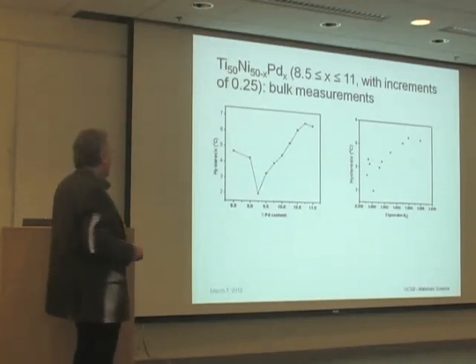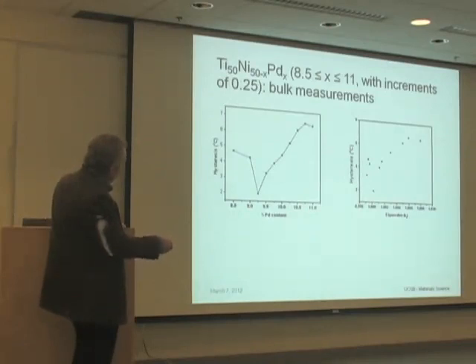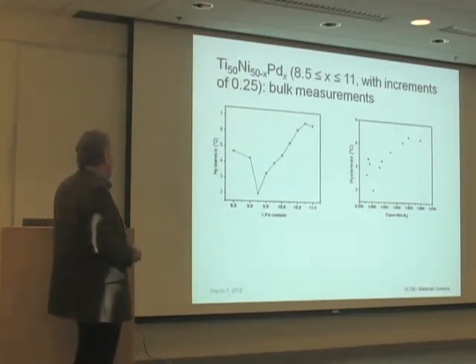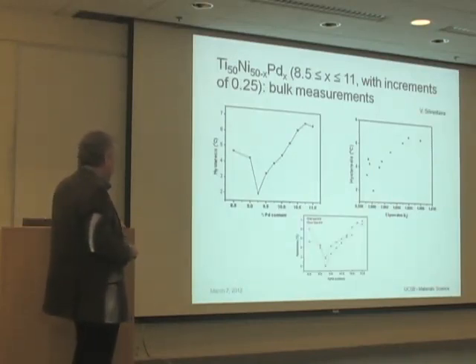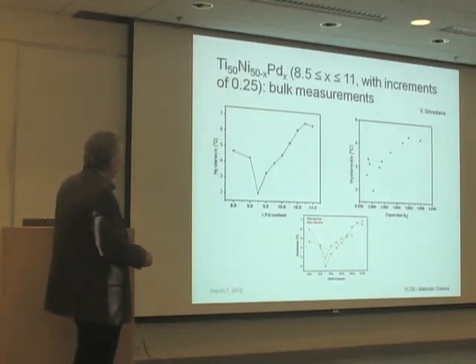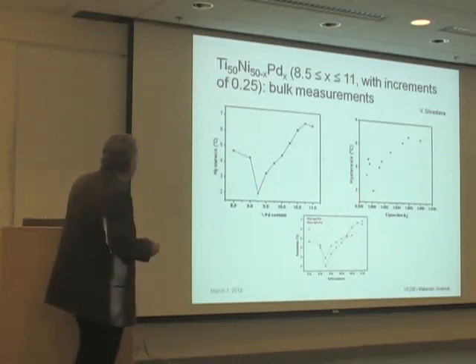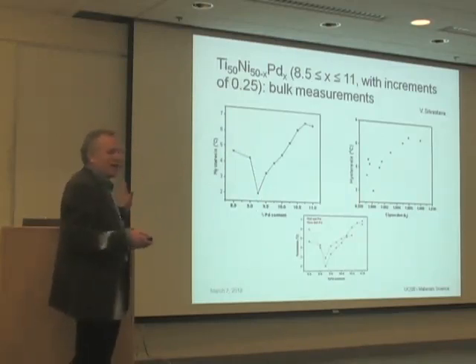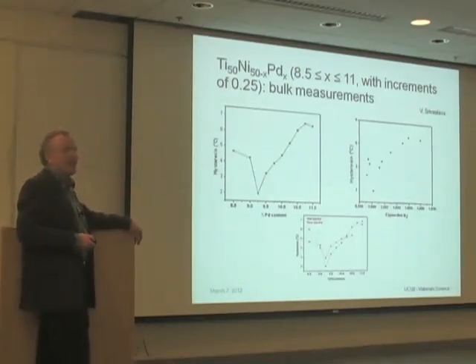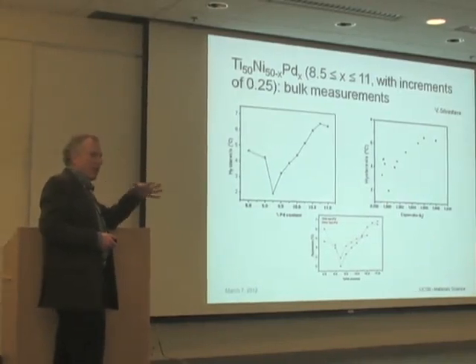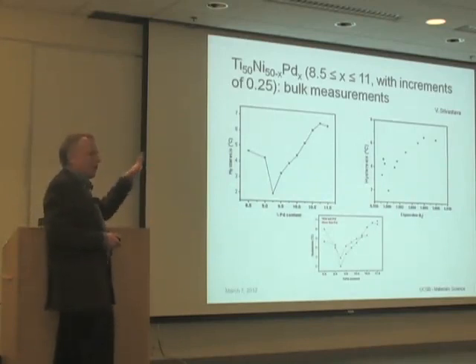And so now that's replotted. That's versus composition. This is replotted versus the middle eigenvalue. Again, there's a very sharp drop. This is a very much expanded graph. It's reproducible. So this one got 3 degrees hysteresis, but it's quite possible if you went in 1/8 increments, you might get even lower hysteresis. I don't know, but anyway, you have to be really close in composition, and that's why people did not notice this previously. Previously, people made a lot of alloys, even in the nickel titanium system, and they didn't notice this sharp drop in hysteresis just because you have to be at a very special composition to see that.